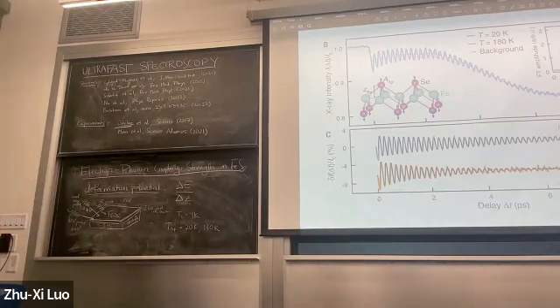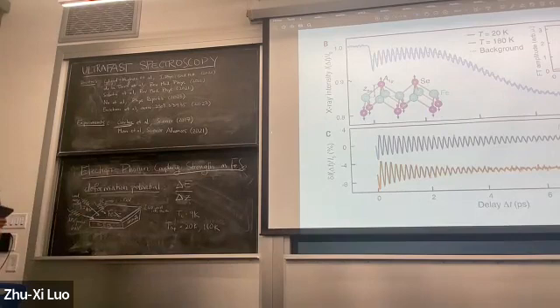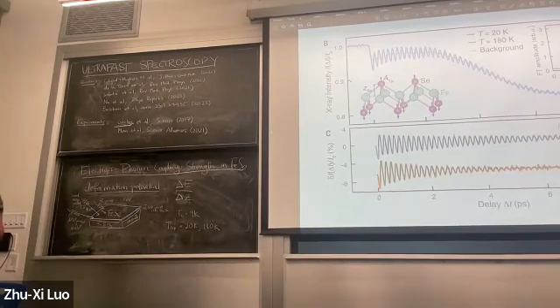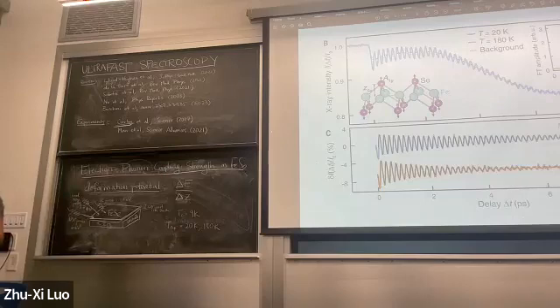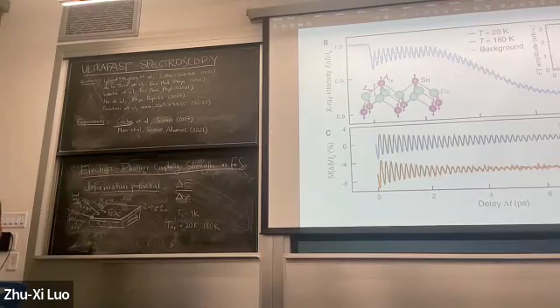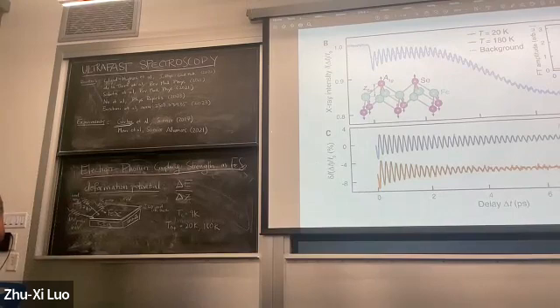Can you repeat what the function of the X-ray probe is? Yeah, so we're doing two simultaneous experiments here. One, a time-resolved X-ray diffraction experiment, where we're going to eventually see the phonon, the oscillations of the lattice due to this phonon that's been excited. And then the UV light is for the ARPES experiment to learn about what the electronic degrees of freedom do. I see. So that's going to be similar to the expected phonon energy.